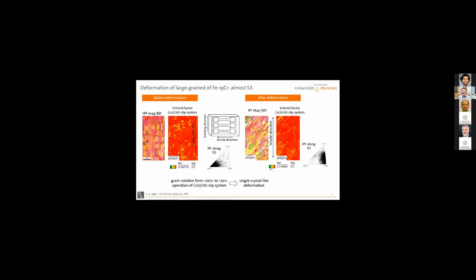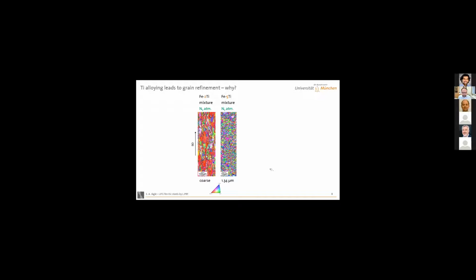And after deformation, if you go back to EBSD, you see exactly the kind of lattice rotation that you would expect from a single crystal deformation. So for me, it was very nice to see this textbook behavior for the first time in my life as a researcher, because I've never worked on single crystals before. All right, but let's look at